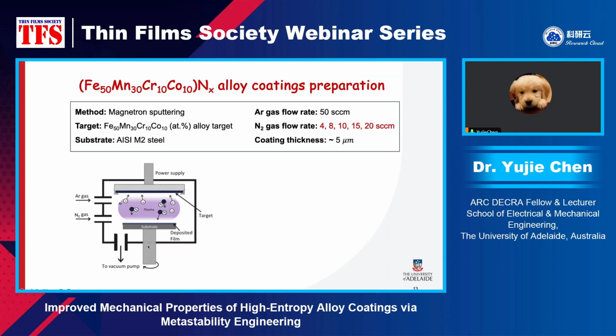So this is a schematic illustration of the magnetron sputtering. I'm not going to discuss too much on this. You just need to know the rapid quenching effect. It will suppress the formation of nitride and promote the formation of random solid solution. But normally, the higher the nitrogen flow rate, the higher the nitrogen concentration in the coating.